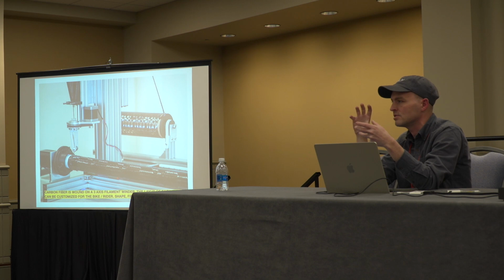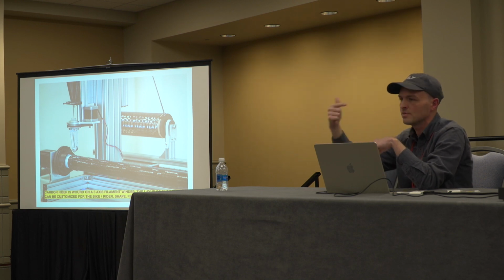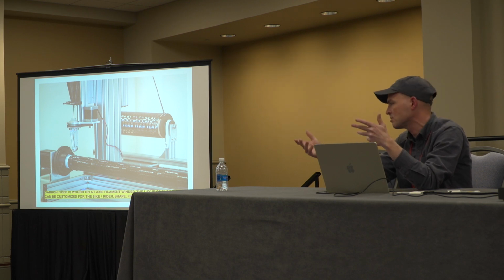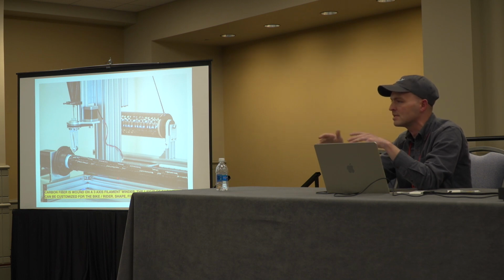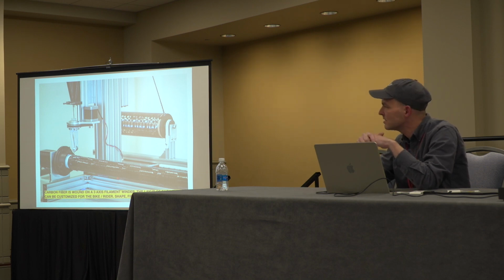So if you want a tube that's going to counteract a twisting force, maybe you would do more layers at a 45-degree angle. If you want a tube that's going to resist crushing, you would do more hoop layers, at a 90 to push back out. So you can really tune the characteristics of the tube on a per frame or per rider basis. And again, I'm not a composites engineer, so this is very much something I'm learning and figuring out, but it's an interesting process.